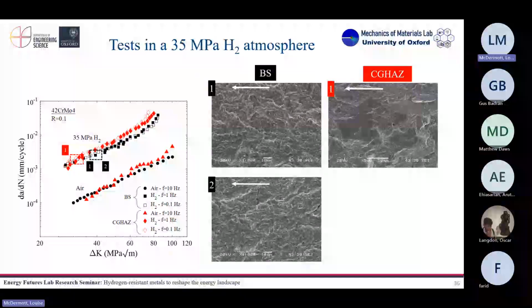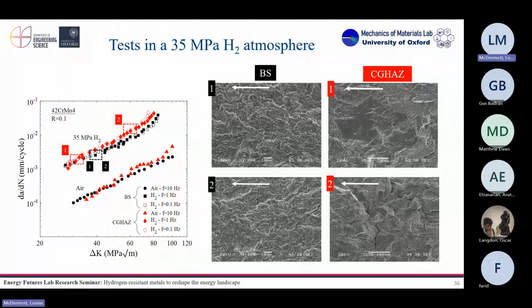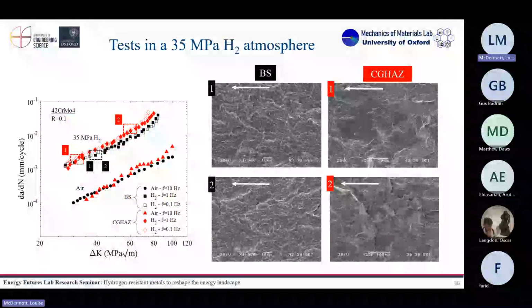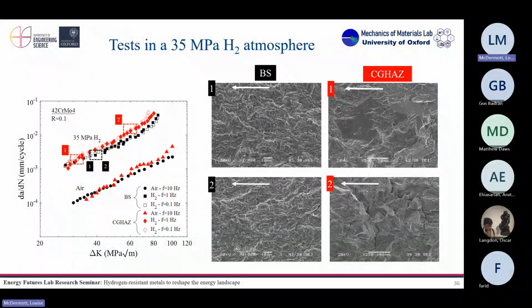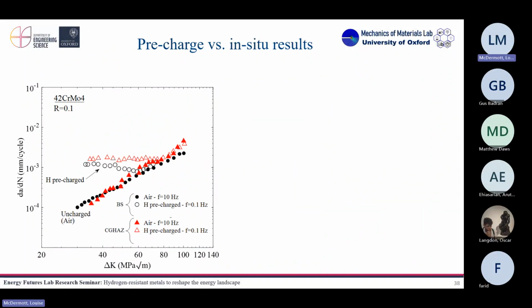And in this case, as it happened before, we have some intergranular cracks and even more brittle behavior than far from the weld. And then we are going to compare, but you can already see that okay, maybe not at the beginning, but after some crack growth, the crack growth rate in my zone close to the weld is considerably higher than in the one far from the weld. So I said, okay, I need to directly compare the results on the same plot. We have the results in air, no hydrogen, then we put hydrogen and then we test, and then we test inside of hydrogen. So inside of a hydrogen chamber. And we see the behavior is completely different.